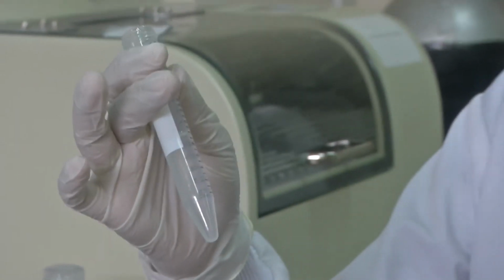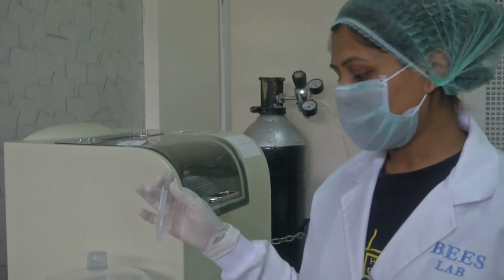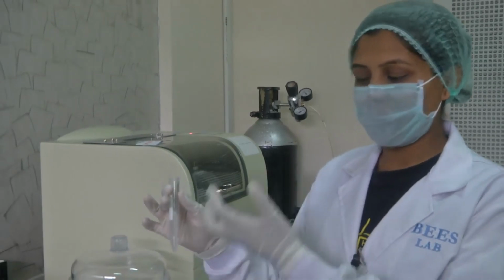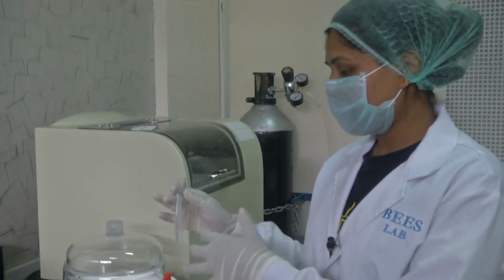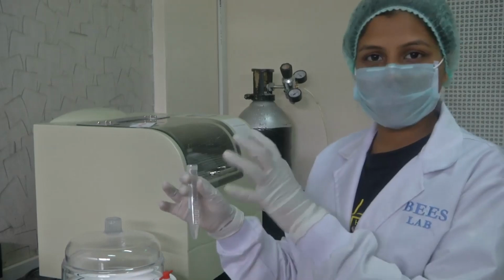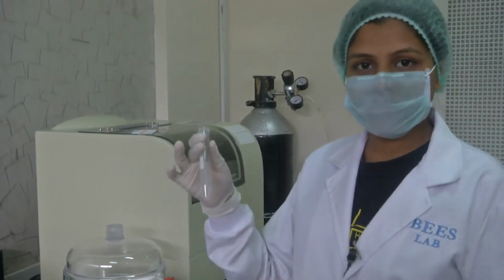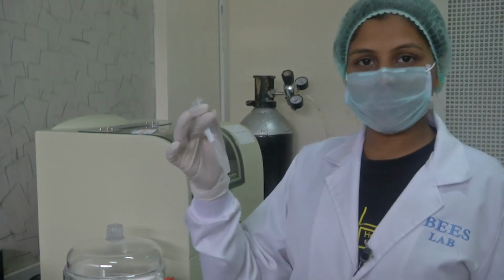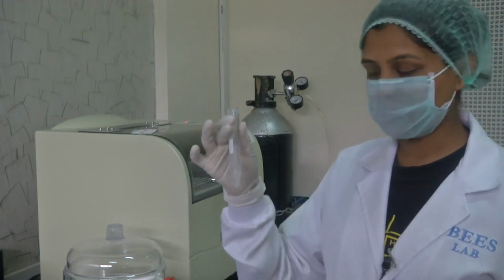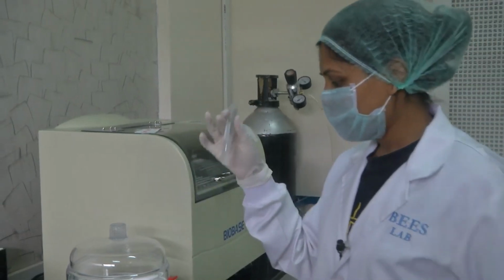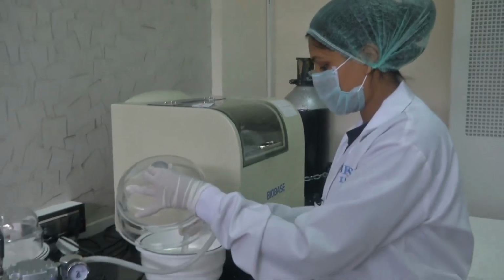So, we follow this procedure called degassing, where the mixture will be put into the desiccator for around 5 to 10 minutes, so that all the air bubbles will be pulled out, and the vacuum chamber will ensure that there is no more air left, and you will see it turn into a clear, transparent fluid. So, now I am going to put this into the desiccator.